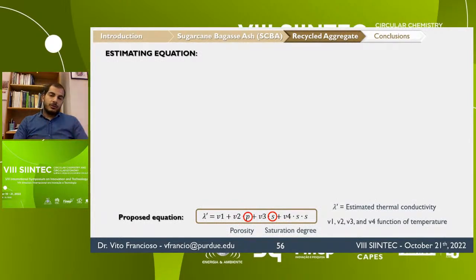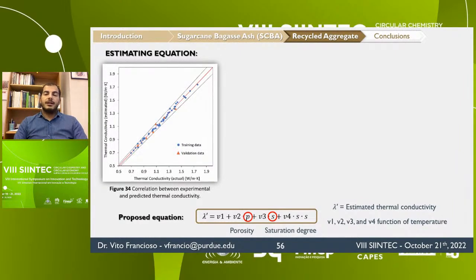Finally, based on the results from the response surface method analysis, where the thermal conductivity was evaluated as a function of porosity and saturation degree for each ambient temperature, I propose an equation that estimates the thermal conductivity of cement mortars as a function of the permeable porosity, saturation degree, and temperature. As shown in figure 34, a very good agreement was found between the numerical values and the experimental results. The two dotted lines represent an error of plus or minus 5%. Therefore, this proposed model is accurate and able to predict the thermal conductivity of cement mortars, knowing the amount of permeable porosity, saturation degree, and ambient temperature in the range of 4 to 43 degrees Celsius.